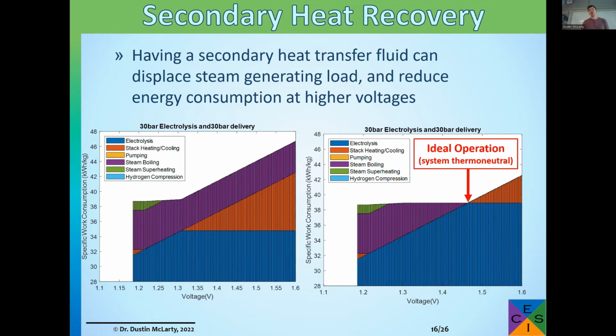Within my lab, we refer to this operating condition here as the system thermoneutral. It's really the peak energy that would balance the energy of the whole system. It's not really a thermoneutral voltage for the stack. The stack itself is actually exothermic in this case, but that exothermic energy is being recovered to provide some of the steam boiling.